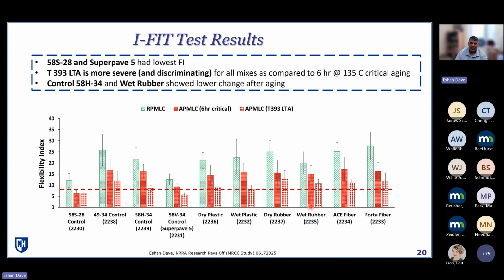Also, I put a line here at 8 because that's oftentimes a threshold that Illinois DOT is utilizing. Now, keep in mind that's typically done for unaged conditions. So all of these were already exceeding that threshold in the unaged or reheated condition. And some people have shown 5 to be the threshold after aging, and most of these still exceed that threshold of 5.